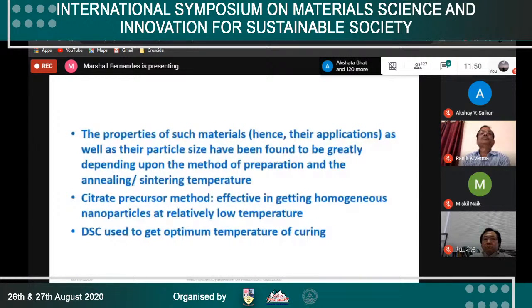And for optimizing the temperature, and for determining up to what temperature the gel or the fluffy mass, the citrate precursor that has been prepared, should be heated, differential scanning calorimetry is used. Differential scanning calorimetry is used to get the optimum temperature of curing. So at what temperature is it?